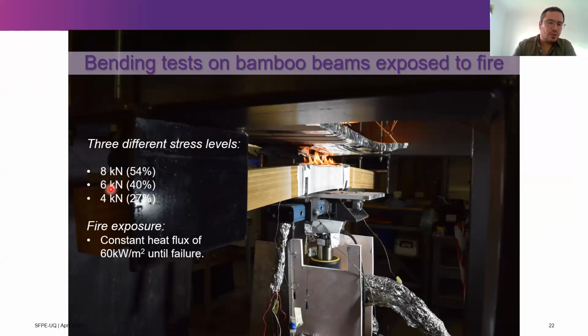So 8 kilonewton, 6 kilonewton, and 4 kilonewton allow us to test 54, 40, and 27% of the failure load. And obviously, we expose those beams to the same external heat flux, which was 60 kilowatts per square meter. What we basically did is apply the load until we reach this stress level, and at that point, we apply our constant heat flux.